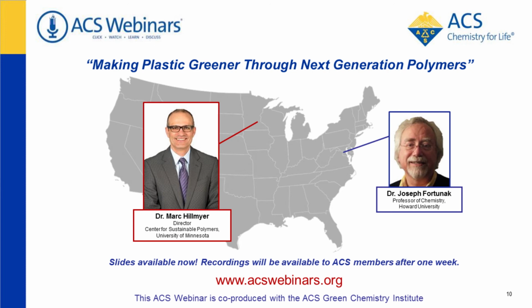Along those lines, people certainly put in additives to polymers that can help prevent or slow degradation during the processing. And I think for different classes of polymers, you may have to develop new benign additives that can help you enhance the processability of the materials. But again, it's a key point that the integration of the center tries to bring. We're worried about that. We made these bars that I showed you about by compression molding, and when we look at the bars before and after the compression molding, we can evaluate how much they've degraded, and in fact, at moderate temperatures, they retain their molecular characteristics very well.